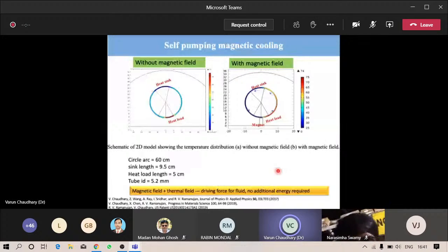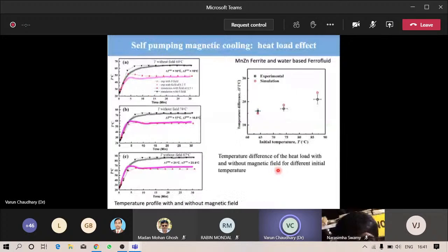Here are the results. For that, we first measure the temperature without magnetic field. So let's say here, without magnetic field, the temperature was 64 degrees centigrade, and then we applied the magnetic field in the beginning. Then the temperature could not reach more than around 48 or 47. So this difference is the heat transferred from the heat load to the heat sink. And the good thing here is that when we increase the initial temperature, let's say here it was 64 and then 74 and then 87, the difference increased.